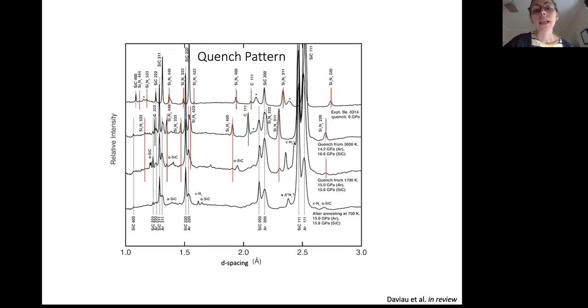And that when you take these samples and then quench them both from pressure and temperature, these phases remain, right? We still have that cubic silicon nitride and that carbon diamond. And this is also consistent with previous work, which saw that silicon nitride quenches to zero pressure after it's been formed.